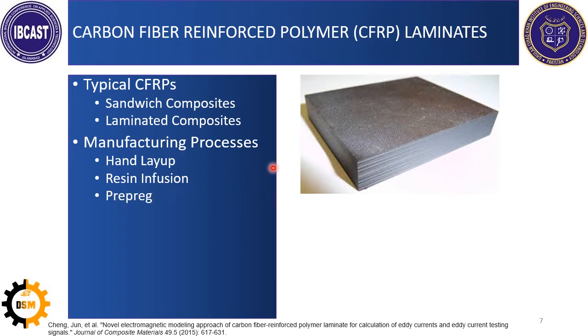The third one is the pre-impregnated carbon fiber laminates, in which you already have the resin inside the carbon fibers, and you just use them like stickers, apply and put the layers on the laminates and get your final property. This is the easiest one to use, but more expensive. It also gives you good properties. Normally, prepregs available in the market need a very specific thermal cycling, and you need a good oven or autoclave to keep your products under pressure to get your required properties of the composites. But some companies are also producing out-of-autoclave prepregs, which are very easy to use.